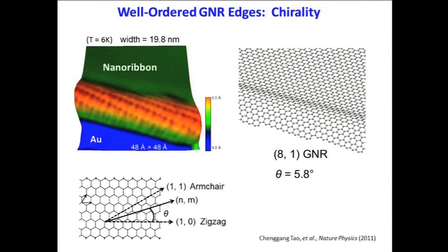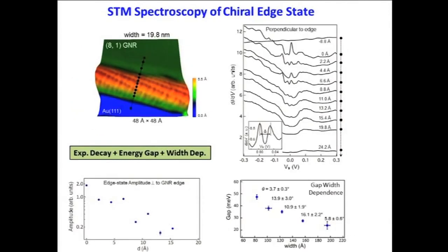And that's about a 20 angstrom periodicity. So now that we know the chirality, we can measure the local electronic structure. And we do that using STM spectroscopy, as I described before, the technique. We perform STM spectroscopy at the edge and then at points as we move inward toward the center of the nanoribbon, as we move in from the edge.